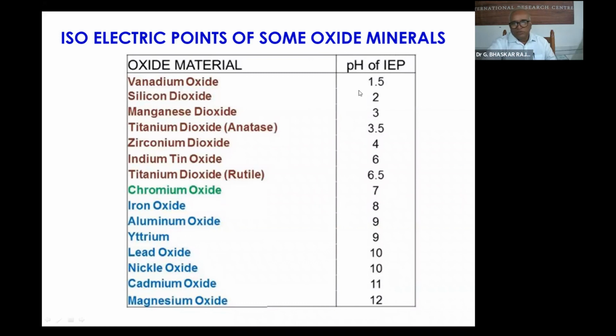This data is very useful when you want to separate one particular material from a complex mixture with different IEP values. If you want to suspend 10 different minerals in a condition, you can suspend them all possessing the same charge, whether positively or negatively charged, so you can disperse them. Once dispersed, by adding a selective reagent, it can diffuse onto that particular mineral, adsorb and coat on it, so that it can get separated from this complex situation of 10 different materials present in the aqueous suspension.